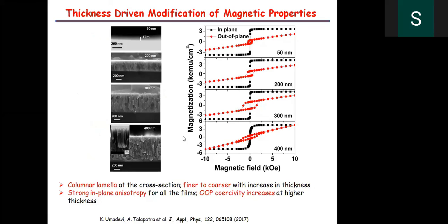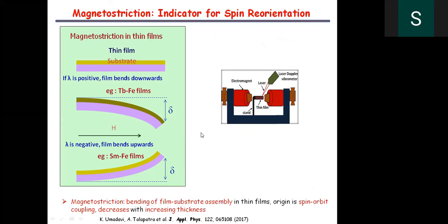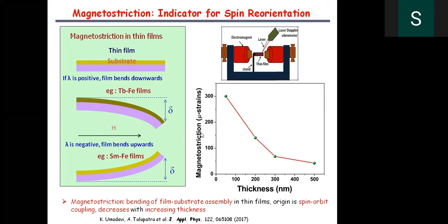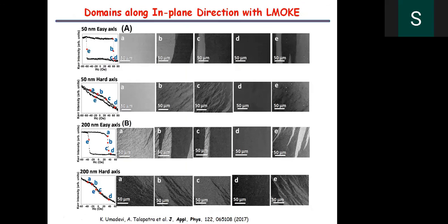To understand this further, we have also carried out a magnetostriction measurement using a laser Doppler vibrometer, and the magnetostriction was found to decrease with increasing film thickness. This basically happens as the out-of-plane magnetic anisotropy is increasing; the overall magnetostriction decreases.